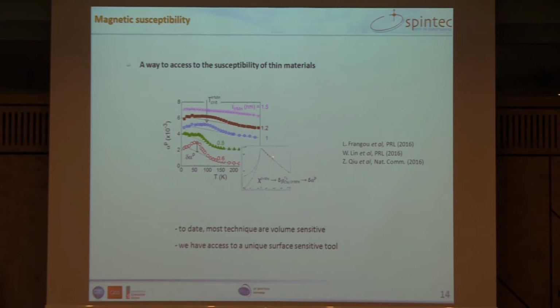Just to make things clear, this magnetic susceptibility does not correspond to this material. This is one of the famous graphs. I mean, Aurélien Manchon likes this graph very much because it's one of the first graphs where susceptibility was reported. And that was reported by one of the co-workers of Néel, which is Bizette. So actually here, we are working out the magnetic susceptibility for ultra-thin and isolated films. That's because we have access to a unique surface-sensitive tool, and to date, most techniques to determine the magnetic susceptibility are volume-sensitive. So I think we really have something here to dig further and to do more fundamental experiments.